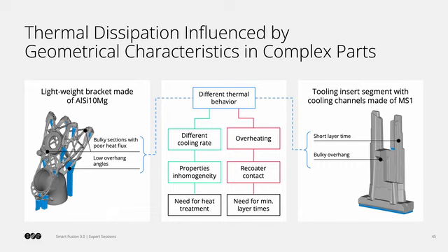A typical example of a part where an AM engineer might choose to add a waiting time is this tooling insert made of MS1. The geometry tapers off toward the top, which means that the time between exposures, often also referred to as interlayer time, is getting shorter and shorter as the build progresses. This also means that the surface temperatures will rise over the build height. Additionally, there's a small overhang region in the center of the part where the heat flux is limited, and as a result, local overheating can also occur. As illustrated, both of our selected applications contain geometric features that can somehow cause overheating.